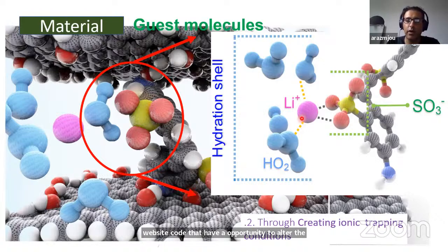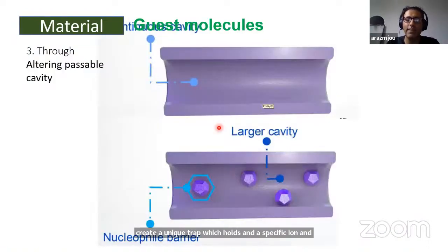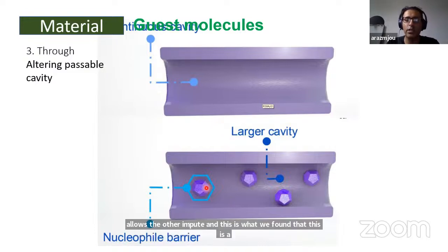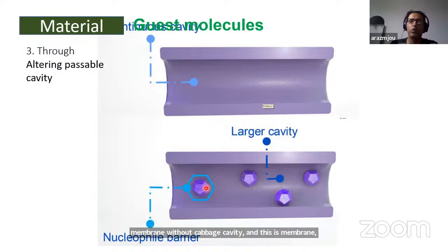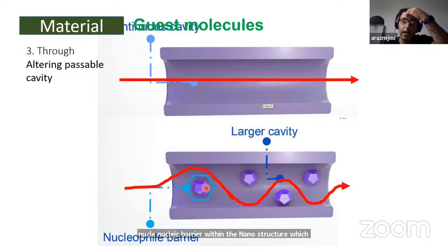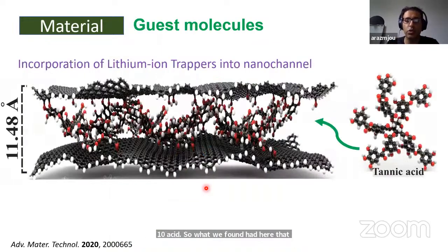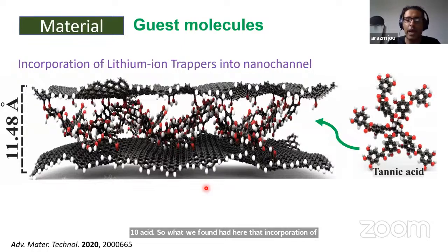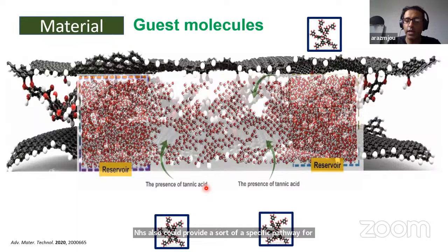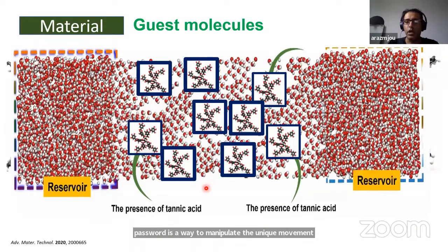And this is what we found, that this is a membrane without cavity, and this is a membrane with nucleophilic barrier within the nanostructure, which alters the structure. Tannic acid. So what we found here is that incorporation of tannic acid also could provide a specific pathway for ions to move through the membrane, and that pathway is a way to manipulate the ionic movement within the nanostructure. So I already covered this one.